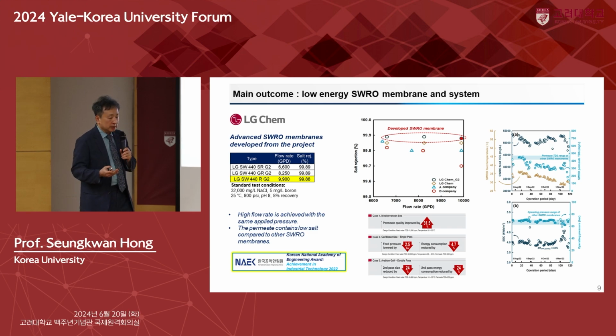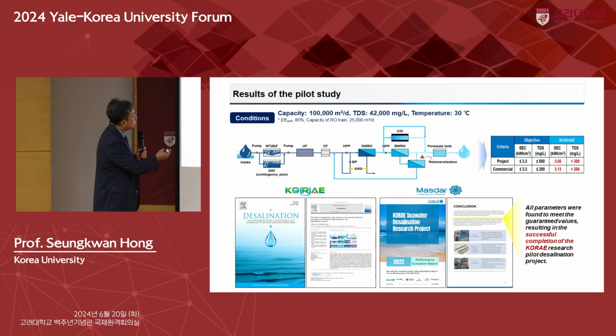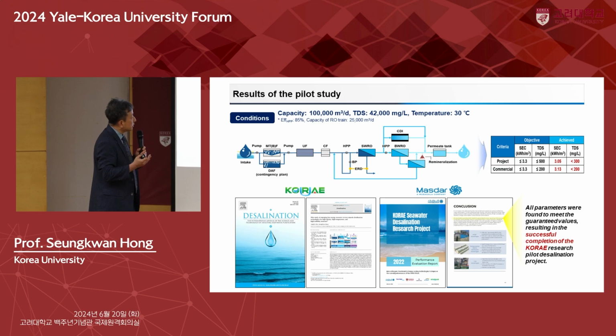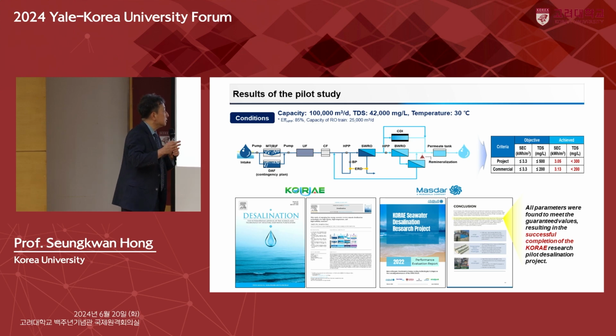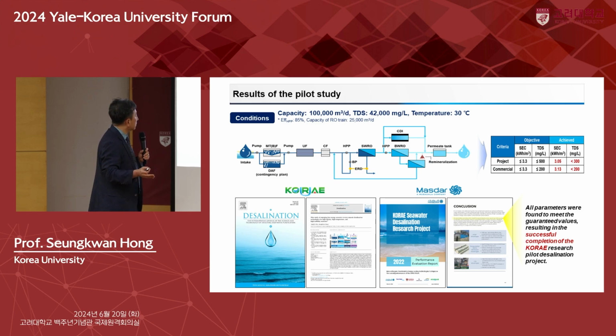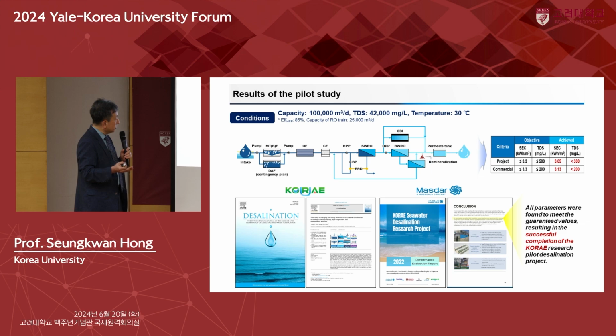By having this membrane in our systems, we were able to achieve the world best energy efficiency, reducing energy further. And here's the final result. As you can see from these tables, we were able to achieve a specific energy consumption of 3.0 under the condition of TDS level below 300 or 200. This has been published in Desalination, and the Masdar company made reports for this project, indicating all parameters were found to meet the guaranteed values, resulting in the successful completion of the KORAE Research Pilot Desalination project.